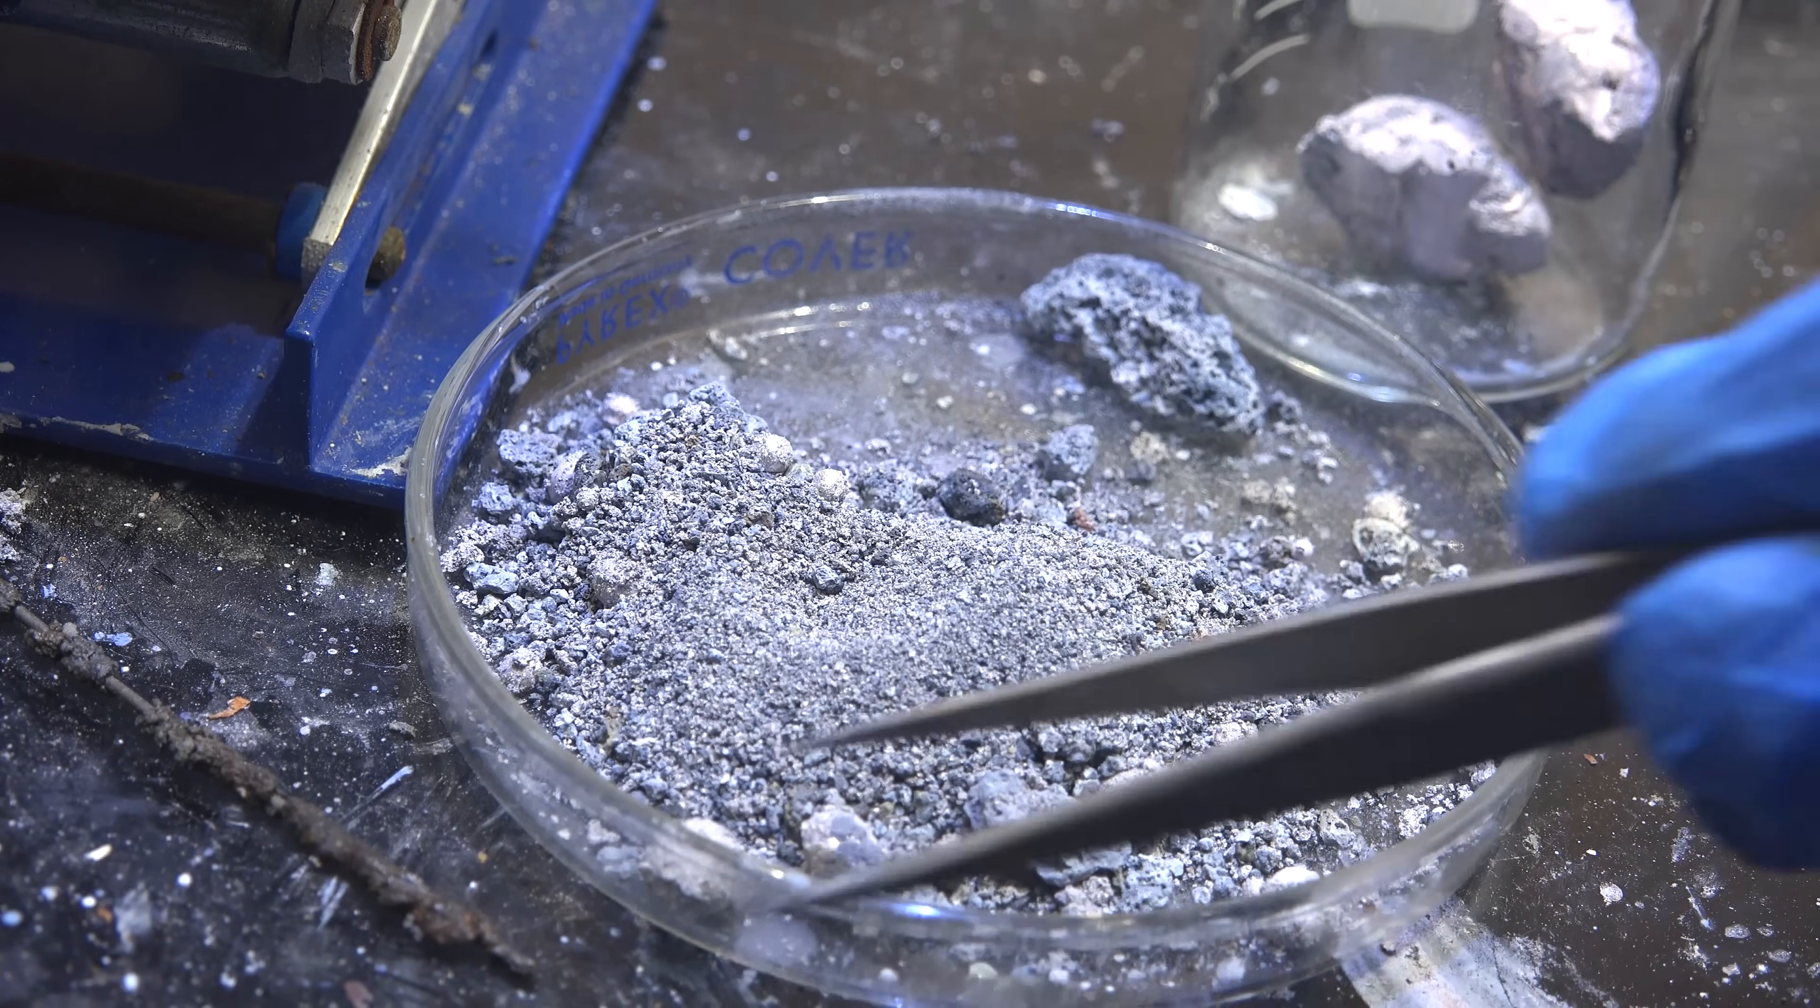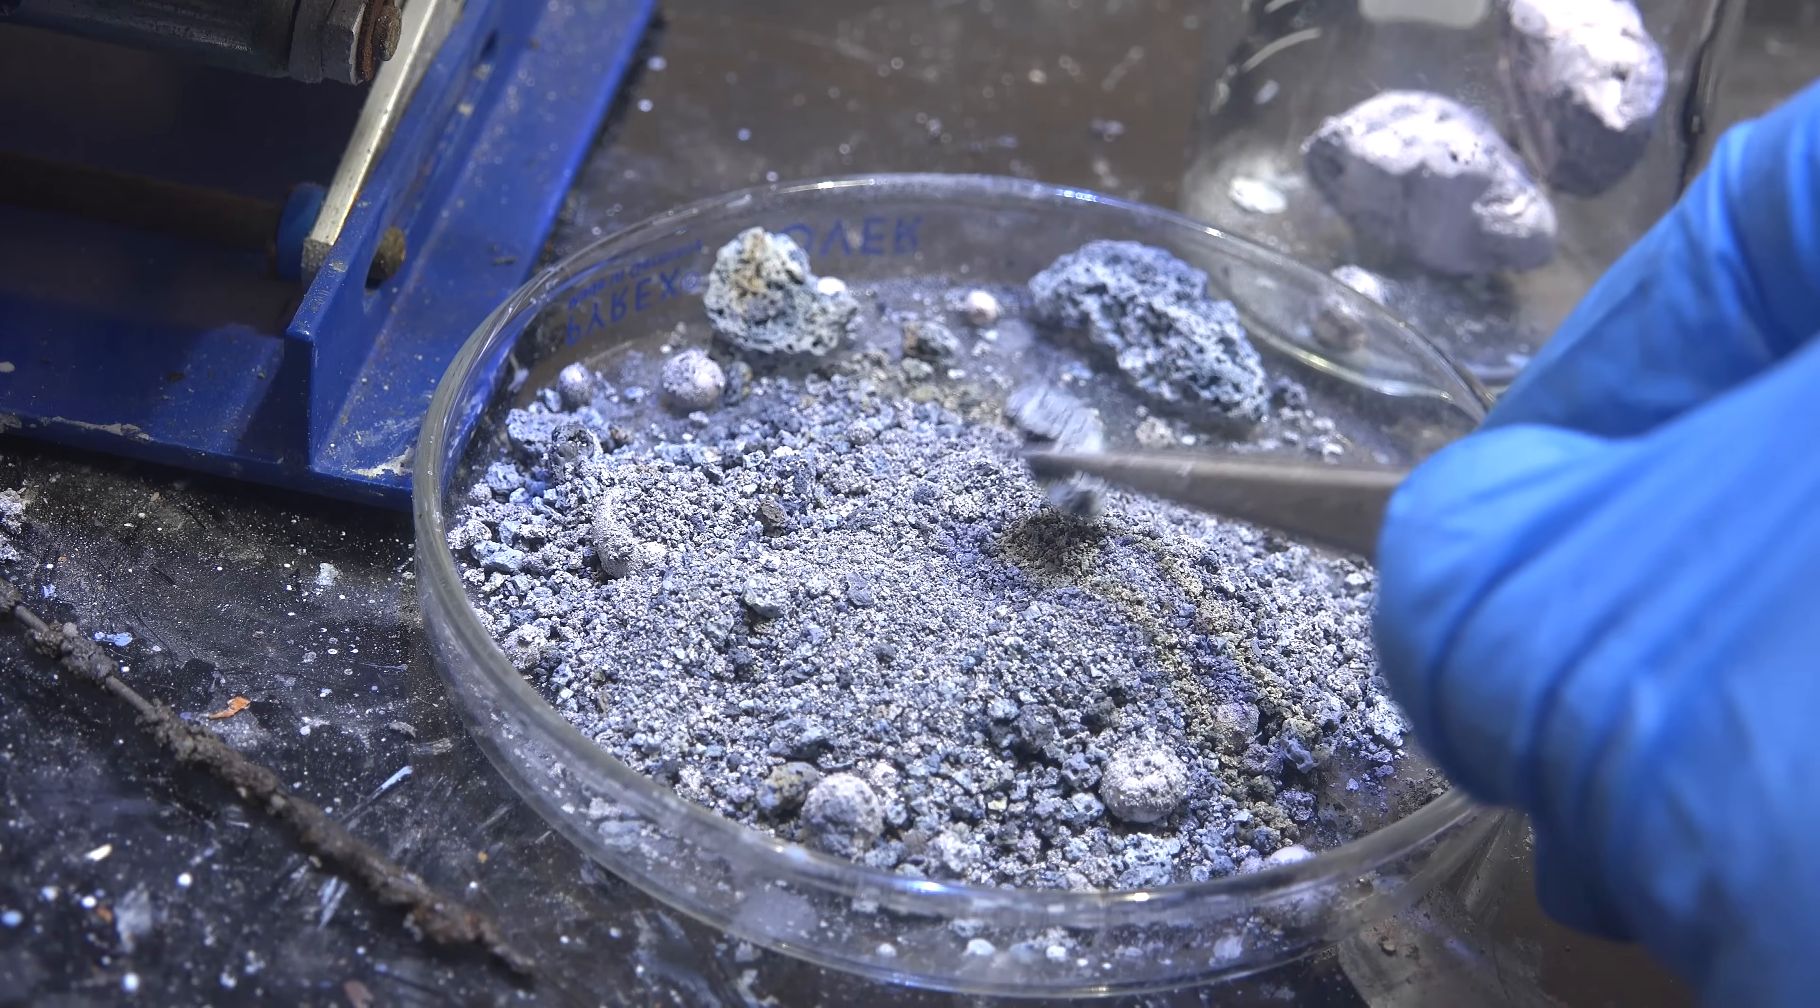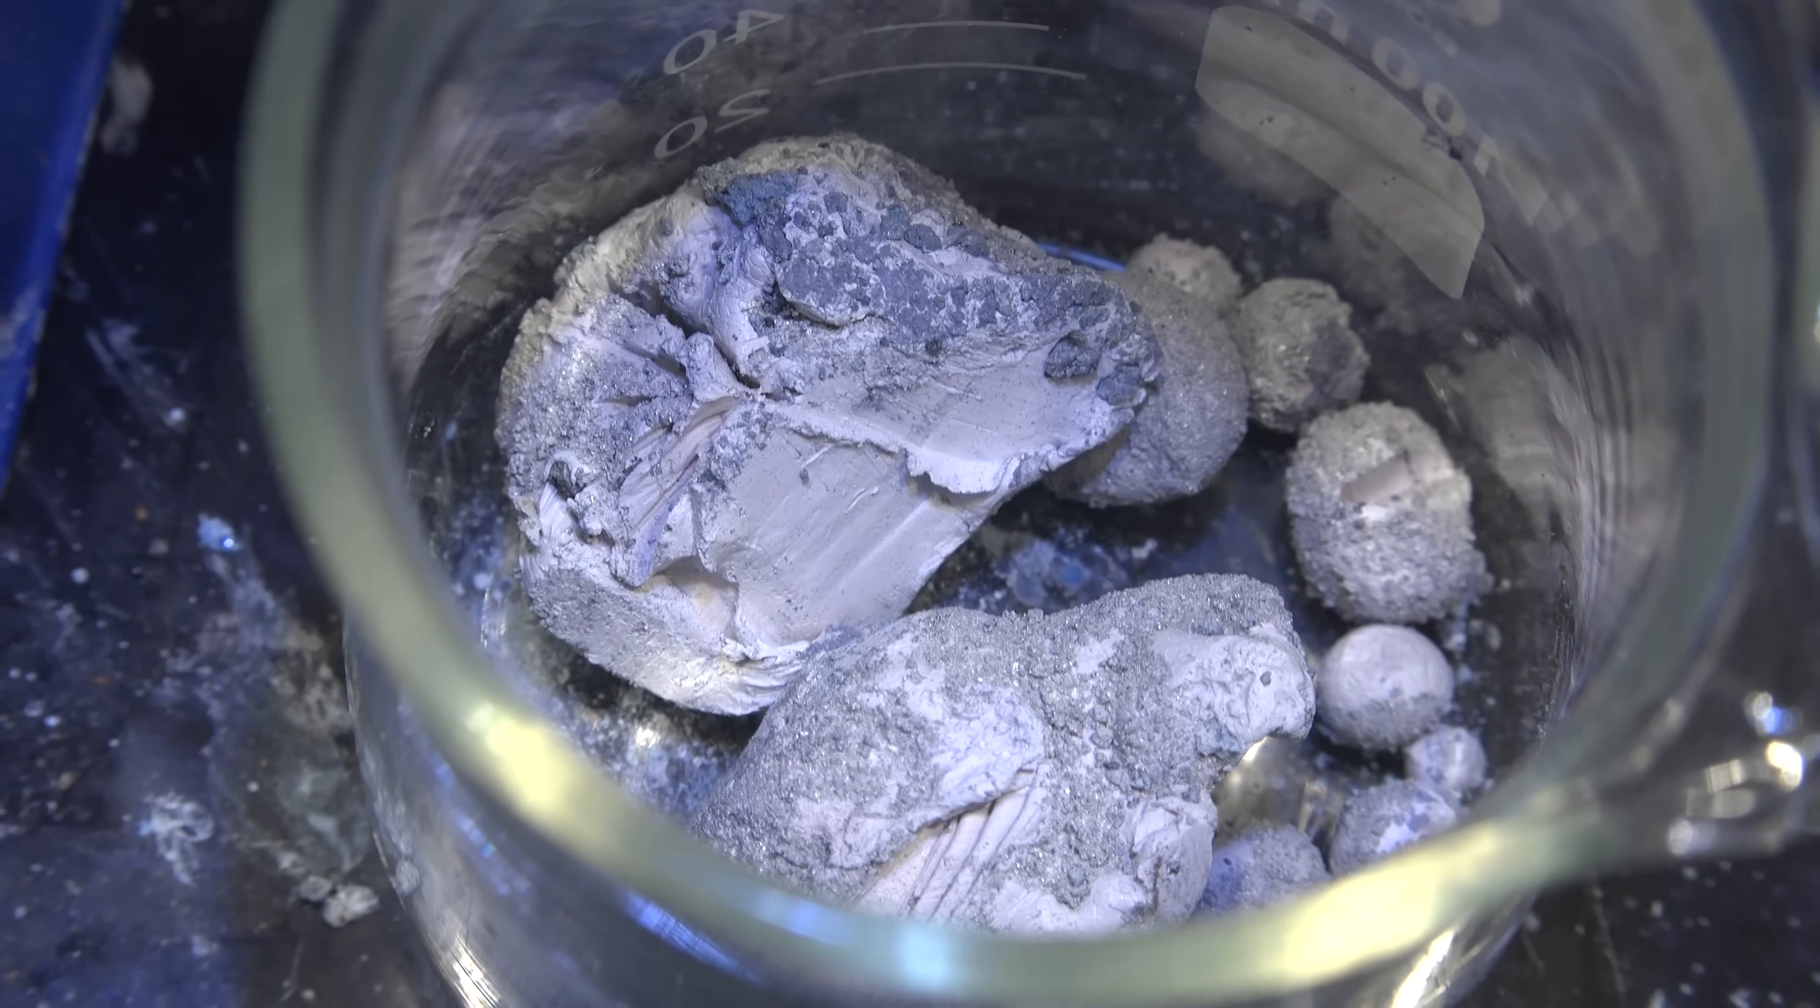But if you're having trouble telling the sodium from the slag then squeeze them with your tweezers. Sodium is soft and deforms easily, like clay. But the magnesium oxide is hard like a rock and if it does give it will break instead of deforming. And there we have it. Sodium metal. It's already starting to oxidize on air and becoming covered in white sodium oxide.